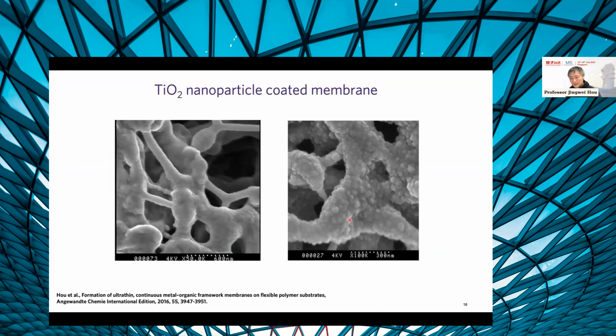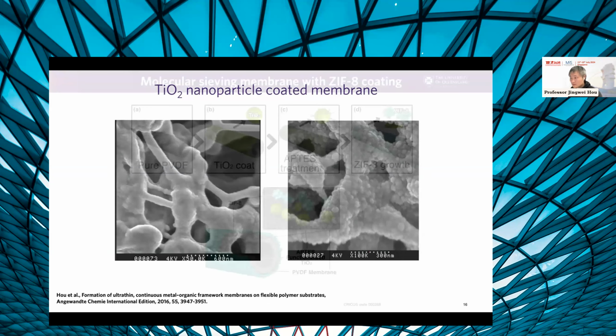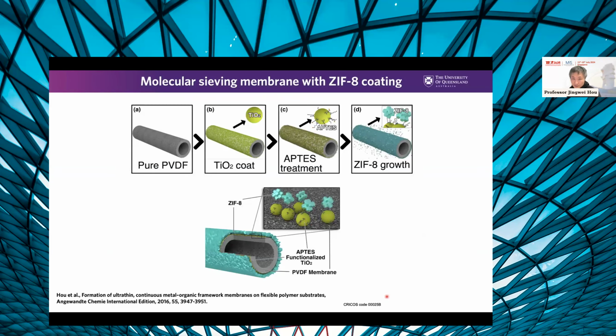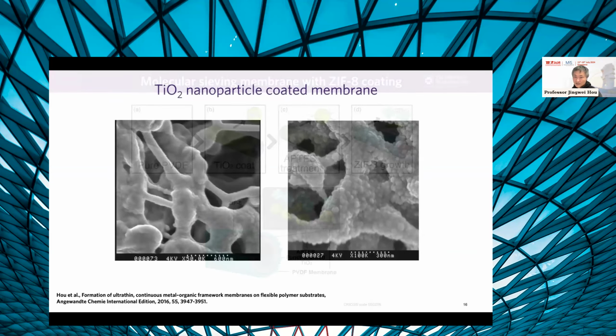One thing is we want to make the polymer and the MOF material like each other more by introducing some intermediate layer in between. In order to do that, we can do it either by physical treatment, that means increasing the surface area, and also we can introduce some chemical bond that can increase their affinity. So we thought, okay, why wouldn't we do both? So this is how I did it. We start with a pure polymer material, and we use a sol-gel coating technology to coat TiO2 nanoparticles on the surface. This is what we get.